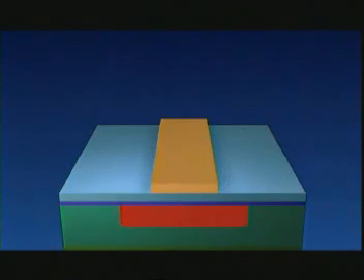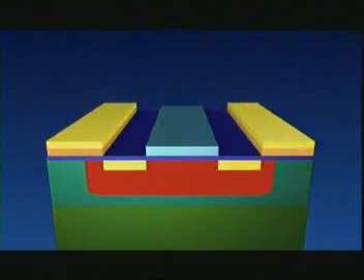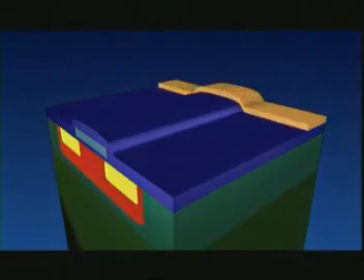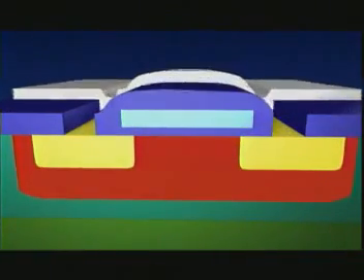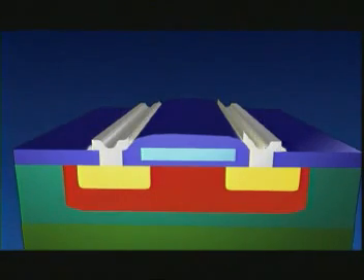A new silicon layer is applied over the oxide layer. And once again, a layer of lacquer is applied, exposed and developed. The silicon which is uncovered by this process is then etched away. Another series of treatments involving lacquering, exposure, bombardment with atoms which penetrate the silicon, new oxide layers, etc., is performed until the whole pattern is complete in all its layers. Some 300 to 400 process steps are required, along with 15 to 20 different masks with microscopically small patterns. The final step in the process is the connection of the various, almost invisible, tiny elements in the silicon. This is how we make an electronic circuit, an IC, or chip.